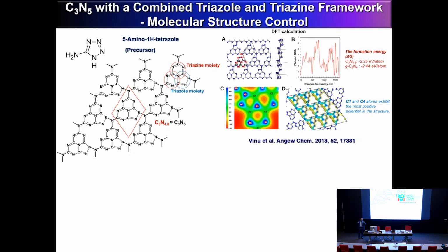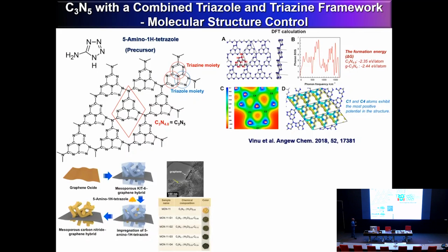It's a kind of wave-like surface on this material, but of course it's a flat structure you are seeing here, but it is not that. Can we use that uneven distribution of the energy density to make another hybrid structure? We have done that by integrating with a mesoporous templating strategy. First, we made graphene nanosheets, and then we put them in the mesoporous silica template, and then with the tetrazole. And once you remove the template, you get that graphene C₃N₅ mesoporous nanostructure.